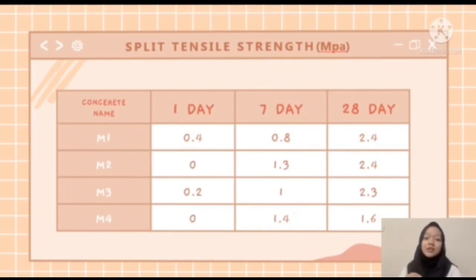split tensile strength of eggshell powder concrete was comparable with control concrete up to 10% eggshell powder replacement. However, concrete with 15% eggshell powder had lower split tensile strength than control concrete.